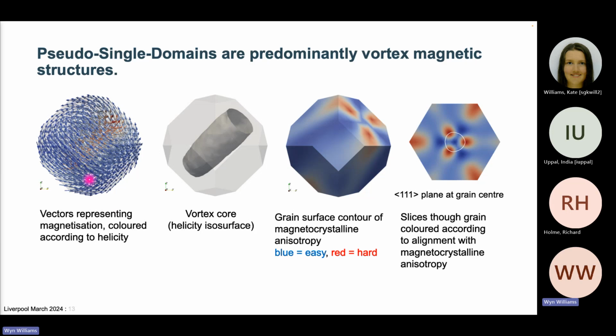So this is just how I'm visualizing it, or Les visualized it. This is the magnetic structure with the magnetization represented by vectors on each node of a finite element. We do a nice surface to illustrate the core of the vortex and its orientation. And these are contour surfaces of anisotropy, where blue is easy aligned and red is hard aligned. So it just shows you how the magnetization likes to align along a preferred crystallographic axis. But it has to move out of those easy directions in order to form different domain structures.